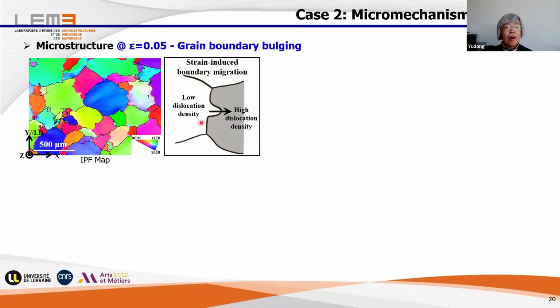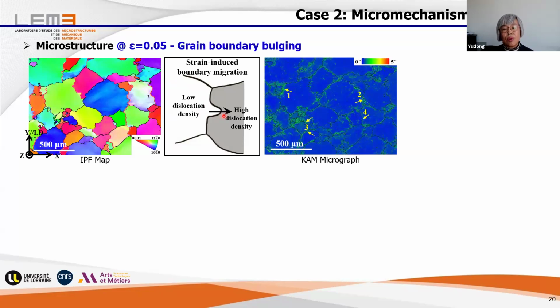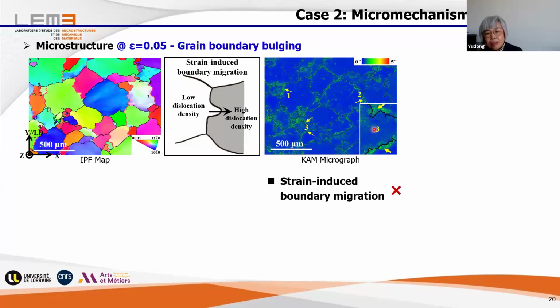In that case, the boundary moves from the part with low density of defects, that means low stored energy, to the part with high density of defects, that means high stored energy. So this is more in the category of recrystallization. Then we made just a very simple analysis, Feng Ming made this. From the enlarged, zoomed picture, you see the situation is exactly inverse. The bulging part has high density of defects, but in front it is lower. So it's not what we thought, strain-induced boundary migration, but another category called stress-induced boundary migration.